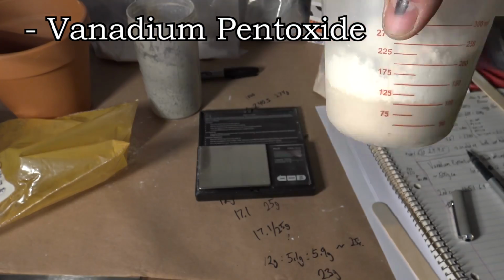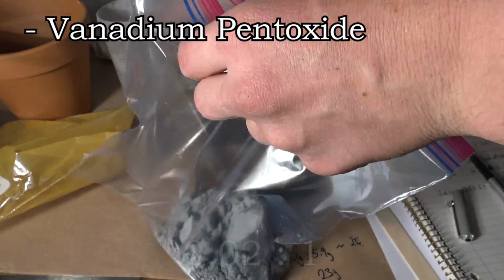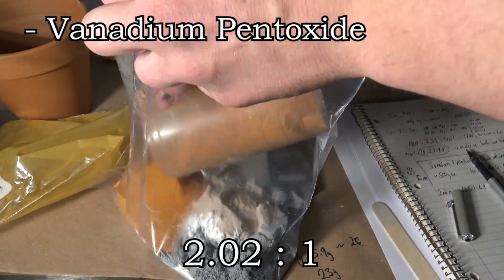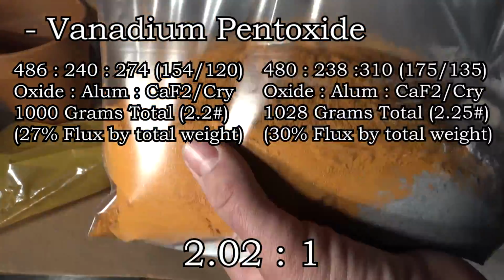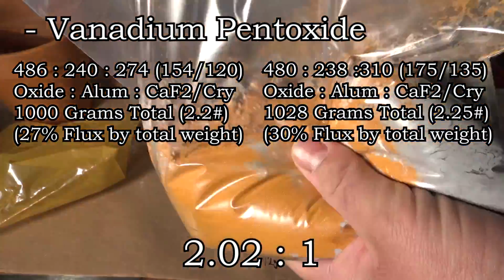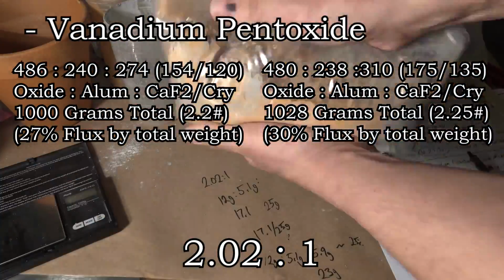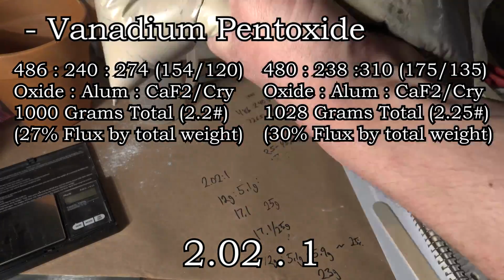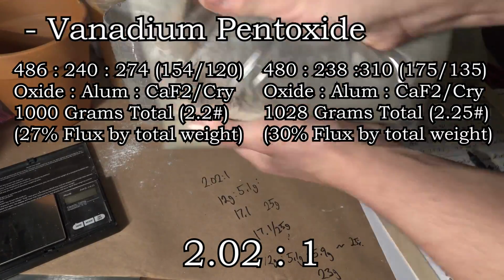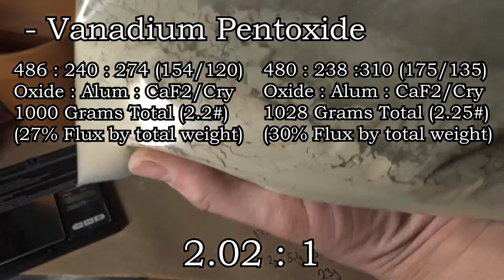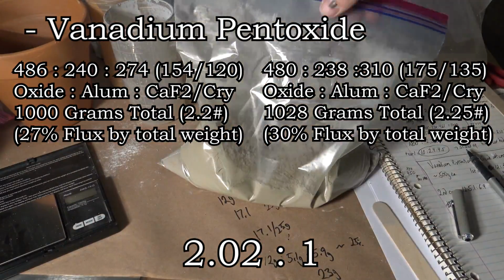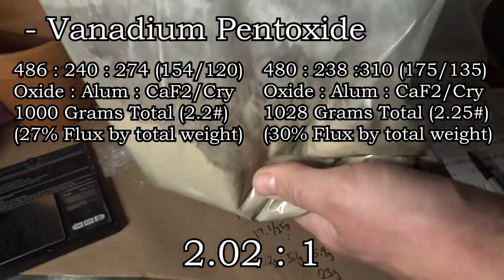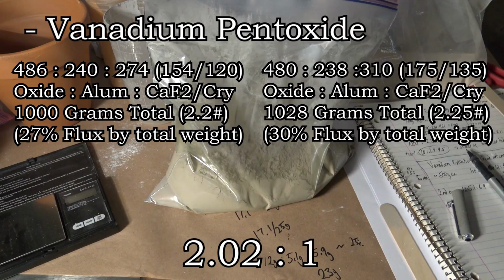So, starting with a stoichiometric ratio of 2.02 to 1 and 480 grams of the oxide for each, we get formulas like you see here. The one on the left uses slightly less flux than the other, as by my previous calculations that was the crossover point from metal extraction to crystal formation. Ideally, one will have a blob of metal in it, while the other should have large black crystals growing in the voids of the slag. Let's find out if it worked.